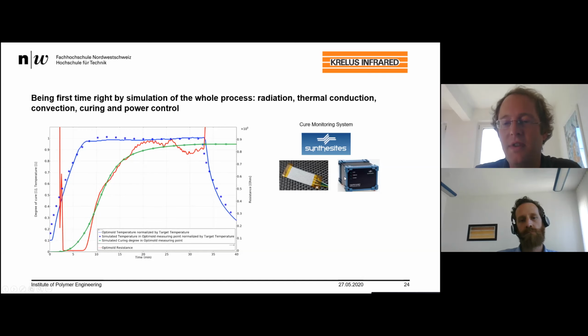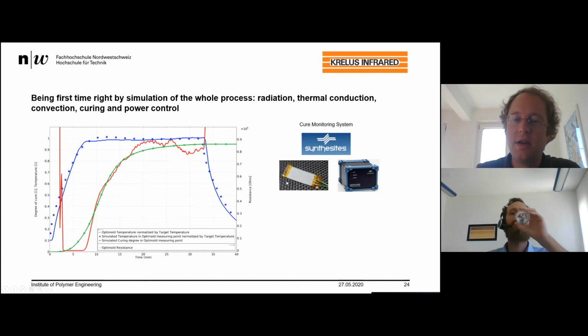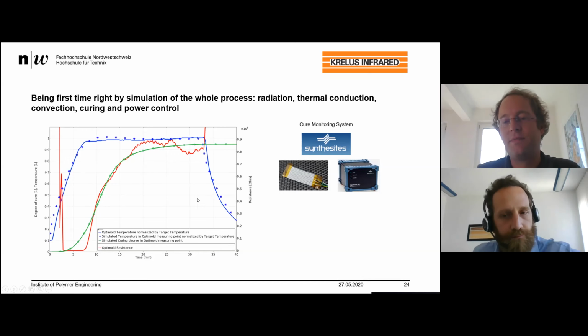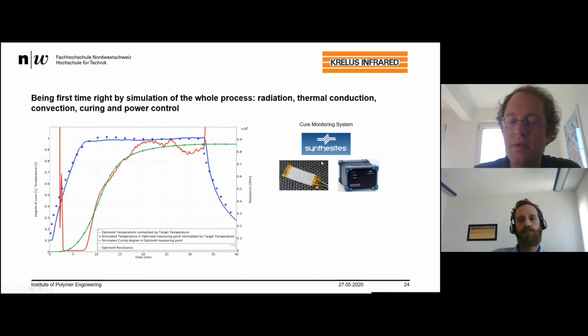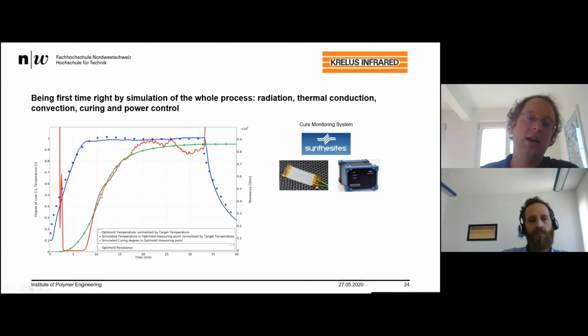And because we have used the cure monitoring system in the trials, we can also compare this to our simulation results. So what we are doing here is using a system from the company Synthesites, which is measuring the change of dielectric properties in the thermoset material. So the resin behaves like a dielectric material, a really bad dielectric material, and you can see changes of the resistance during the curing process, because the mobility of dipoles and ions starts to decrease, and therefore the resistance increases. The red line represents this change in the resistance, and the green one is the simulated degree of cure.